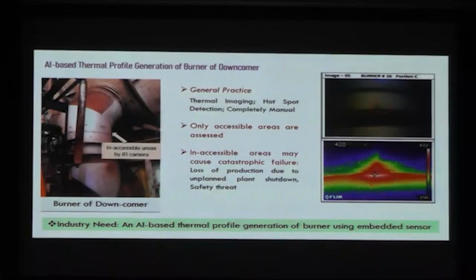Similarly, this is a structure, and you can see how big. This is again a refractory lined structure. Actually, what happens, these are all refractory lined structures. The refractory erodes, and when it is eroding, where it is eroding from, nobody knows. So that erosion causes high temperature at the shell, and that shell temperature we are basically monitoring for giving the predictive model. In this case, you can see most of the area is very visible, though it is at a height of maybe 20 feet or 50 feet, but accessible.